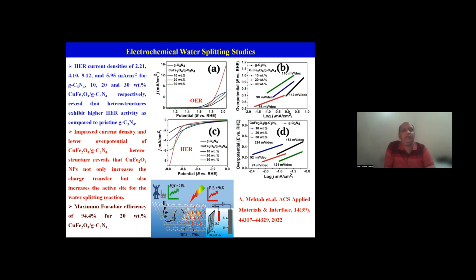Here these investigations suggest improved current density and low potential for the copper ferrite with the graphitic carbon nitride heterostructure. The copper ferrite nanoparticles not only increase the charge transfer but also increase the active sites for the water splitting reaction. So again, these binary heterostructures exhibit high HER activity as compared to the pure graphitic carbon nitride, and we have been able to obtain a high Faradaic efficiency, which is close to 95% for this material.